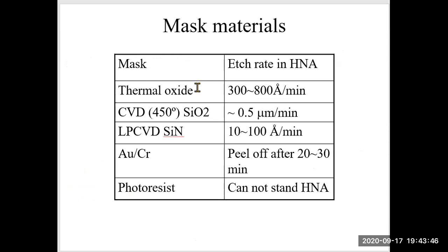Mask materials, namely materials which can be used as the masking layer for HNA etching. First is thermal oxide, actually silicon dioxide. Its etch rate in HNA is 300 to 800 angstrom per minute. Actually pretty high etch rate. That's because HNA contains HF, and we know that HF etches silicon dioxide. So if we want to use a thermal oxide as a masking layer, it has to be thick enough.